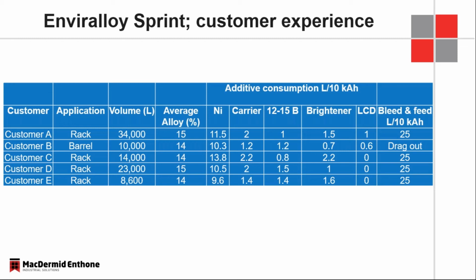So a couple customer experiences, and I think this will go in line with my previous slides. Out of these, only one is barrel, but if you notice, they don't do any drag out. The rack customers, rack plating doesn't drag out that much, so we're looking at 25 liters per 10,000 amp hours, which is about what we were expecting. And the NI, the nickel additives, we've seen that are pretty much in line as well. You can see the bottom customer is below 10 liters per 10,000 amp hours, but all the other experiences, whether it's an 8,000 liter or a 34,000 liter bath, are all fairly consistent. And the ratios between the carrier and 1215B are approximately what we would expect as well. The overall add backs are not a lot for this system.